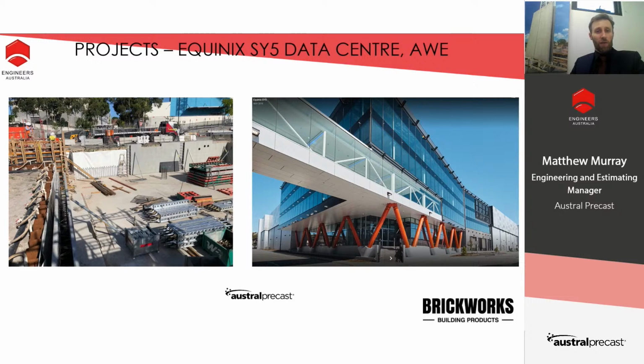And so here we can see one of our first data centers we did with double wall for AW Edwards for the Equinix SY5 data center in Mascot in Sydney. For this project, we used double wall both for the retaining tank walls. So that's the picture on the left-hand side. These walls are actually the water retaining tank for the cooling liquid for the data center. But we also use the double wall for the shear walls internally in the building. So every shear wall that connected to a large precast column was double wall with a wet joint to connect the two together, which completely eliminated the use of any cast-in plates on site and any hot works for the double wall and column interfaces.